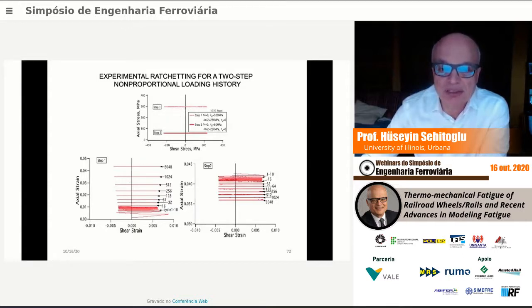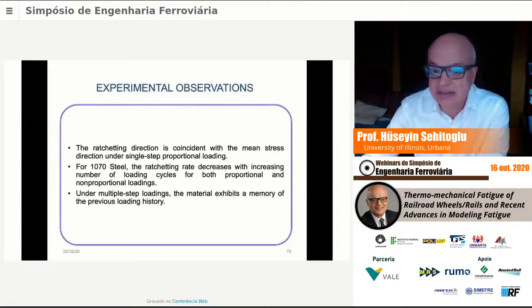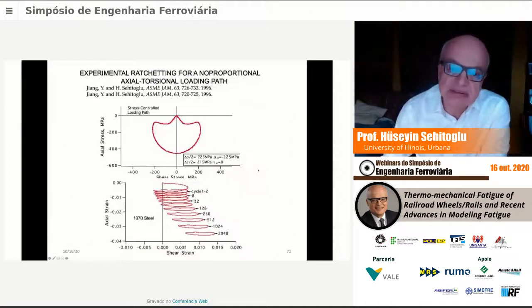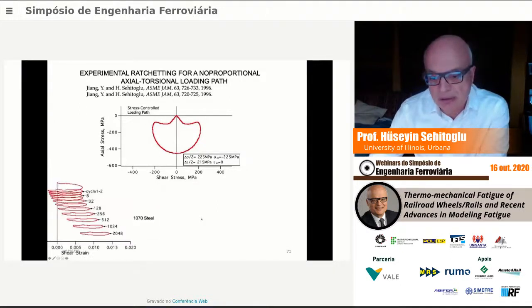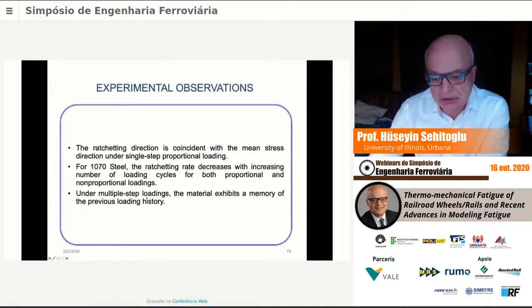One can do, it gets complicated. You do this first, step one, and then you do step two. You get transient effects. So this is step one. It's ratcheting in the way it's shown here. Because axial stress is kept constant, it should ratchet in the tensile direction. Tensile mean stress means tensile ratcheting. But when we lower the stress, still tensile, it starts ratcheting in the other direction. So the material does very, very complicated things, right? So we wanted to develop a model that captures all of these behaviors. We said that the ratcheting rate decreases with increasing number of loading cycles. That was clear here, right? So between 1,000 and 2,000, we ratcheted in the shear from here to here, but between cycle 1 and 500, we ratcheted a lot.